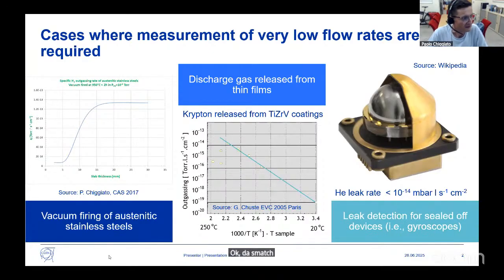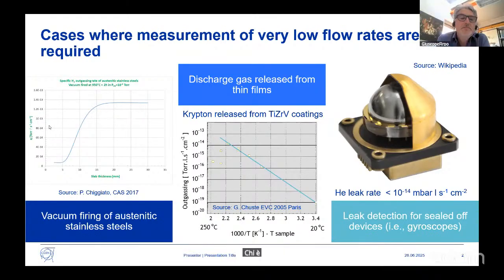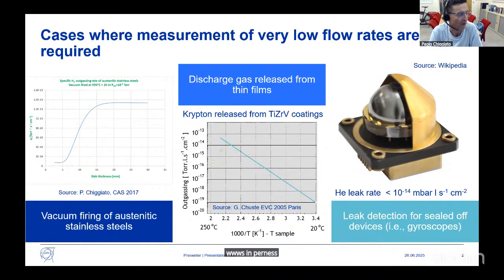Okay, so here you can see the typical outgassing rate, measured in torr-liter per second per square centimeter, of a slab of variable thickness for hydrogen after firing at 950 degrees for 2 hours in a furnace, with an ultimate hydrogen pressure of 10 to the minus 5 torr or millibar at that temperature. What you see is that when the slab is thin, lower than 5 millimeters, you have an outgassing rate in the 10 to the minus 15 millibar liter per second range.